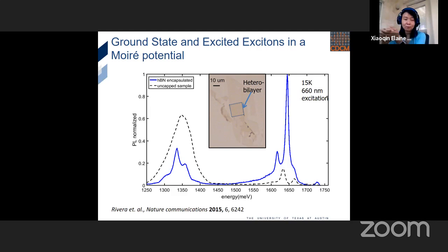I should say that there are people who already measure G2 of the Moire crystal, but I don't believe those experiments prove they're single emitters, because it's still a far-field measurement. And it's odd to me that you can excite 500 of them and get a G2 measurement. I think those measurements are actually selectively picking out the defect states that are present in the material. Okay, great. So thanks. There's some emission that is bright enough for people to do G2 anti-bunching experiments.